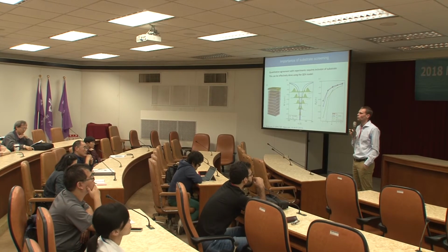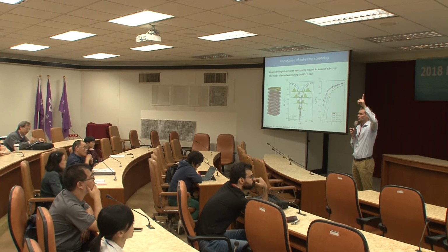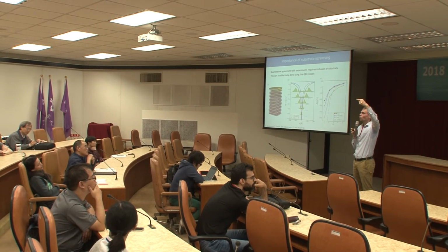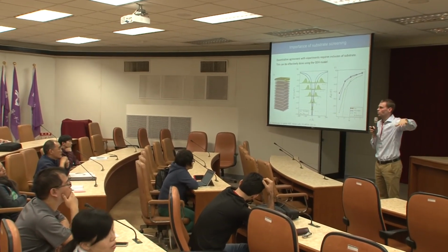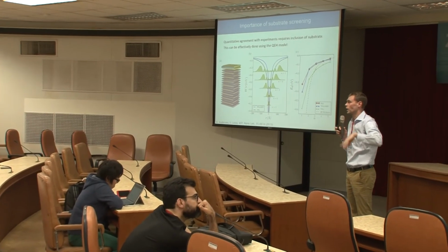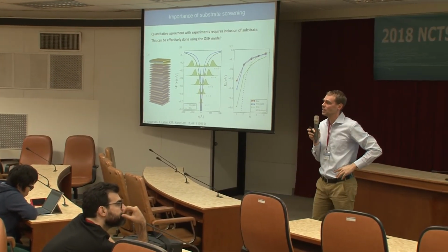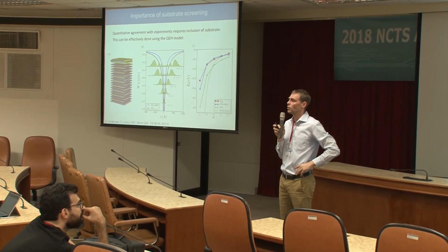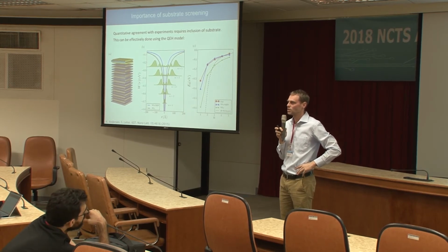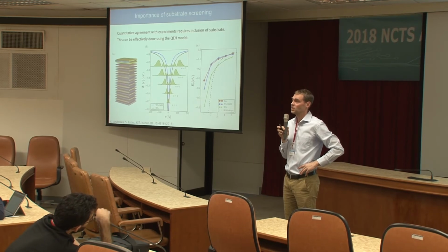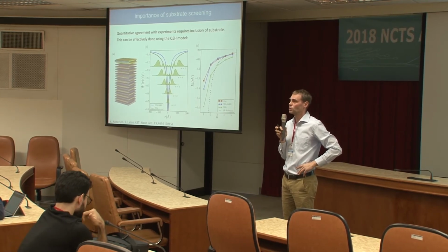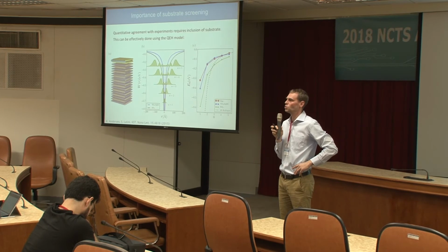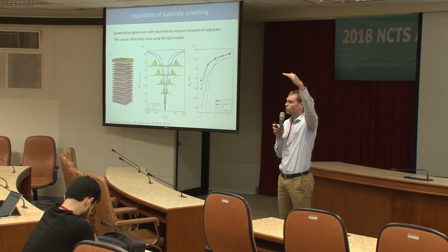That means we have a 1 over r that is truncated in the z direction, so it's a step function. This means electrons in two periodically repeated layers will not interact with each other, whereas in the in-plane direction, it's a 1 over r. This is very important, I didn't mention it, and it's actually the reason why you see this very slow convergence of the band gap with respect to K points. I'm reading many papers in the literature where people are doing GW calculations not using a truncated Coulomb interaction, and in this case they find that the quasi-particle gap converges very quickly with the number of K points. That's also true, but it converges to the wrong result, because it converges to the band gap of a superstructure of layers with some vacuum in between.